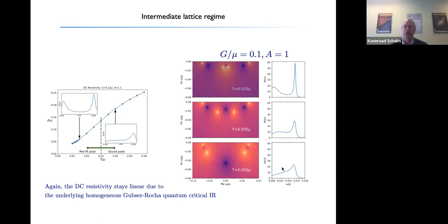But even so, throughout the system, if you look at the DC resistivity, so the value of the conductivity at omega is 0, you see that this essentially stays linear for a large part of this regime. And again, this is completely understandable in terms of the scaling behavior of the underlying Gubser-Rocha quantum critical IR. And this also then is the reason why we can with confidence say that if we could numerically track this down to lower and lower temperatures, we fully believe that this linear in T regime would continue. And actually these points that seem to deviate from linearity, we have reason to believe that they're not reliable numerically. This is where numerics started to have serious issues.